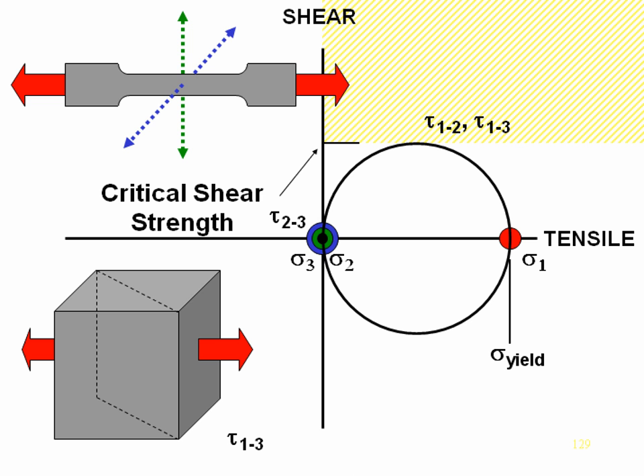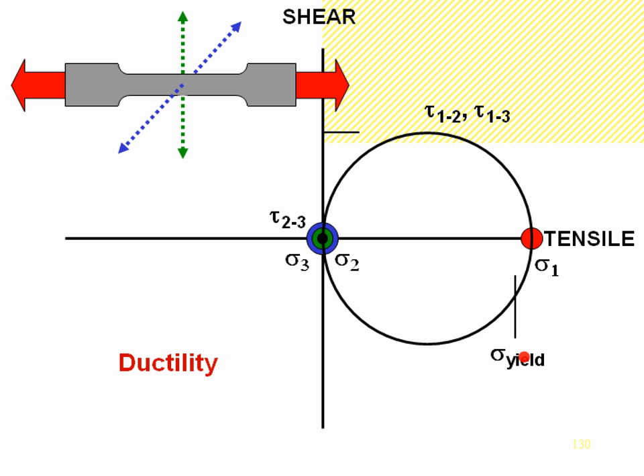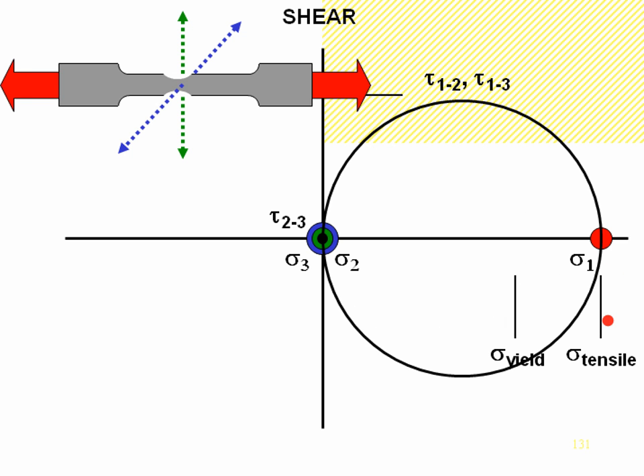Now, let's increase our stress, sigma 1, even further. We're clearly into this area where we can now exhibit ductility. And if I increase my stress even further and I get out to the tensile strength capacity, then finally I start to get necking in this area. I'm getting a lot of deformation along these shear planes. I've experienced ductility. I increase load a little bit more, and bang, this thing breaks. I experience fracture. Now, this should be simply a reiteration of what you learned about Mohr's circle and what you learned in materials lab, and explains that tensile coupon we started with.